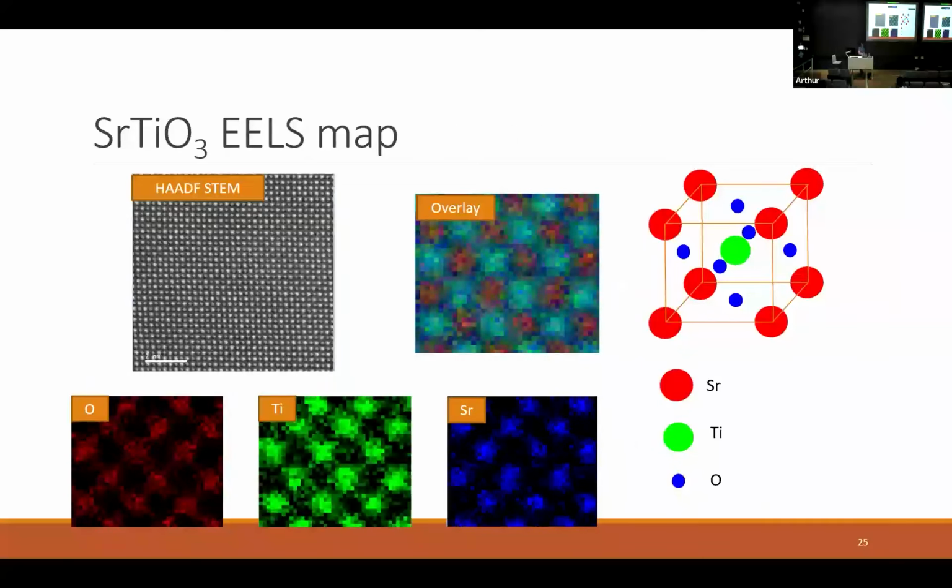And then if we push that to the resolution limits of the STEM, we can start to ID different individual atoms even. So this is strontium titanate. This is another one of my favorite samples to look at in the STEM. This is the HAADF image where you can see these slightly brighter and darker elements. This corresponds to strontium, which is the heaviest, and then you've got the titanium, which is the green here. I do realize that I've miscolor coordinated everything here.